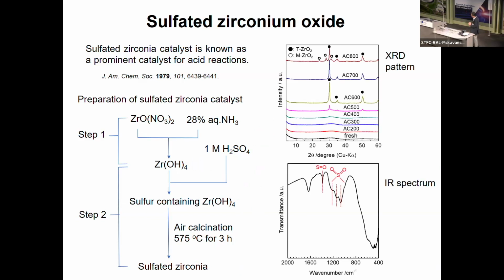XRD phase, very simple. After calcination, the material simply showed the zirconium oxide phase, which is in tetragonal phase. Nothing else, just a simple zirconium oxide. No information about sulfur. Sulfur's information comes from the IR spectrum, but this is really simple information. We cannot guess anything.